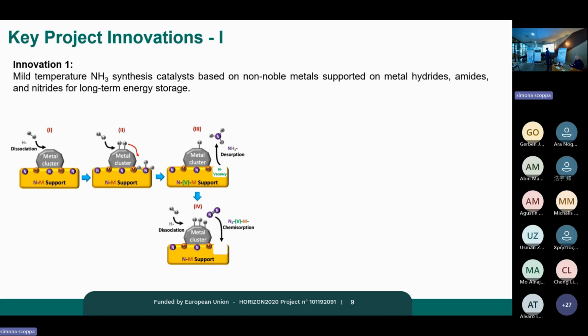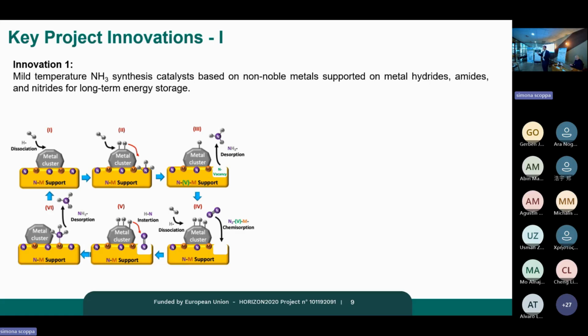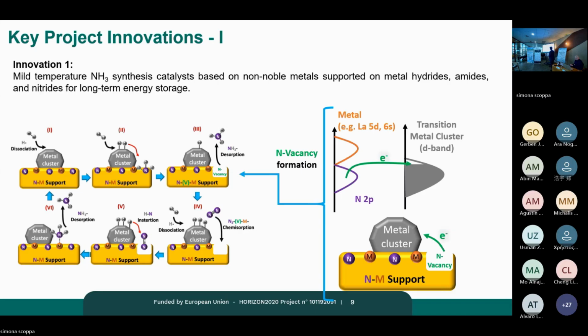the nitrogen, and in that way you can now form a regeneration of the metal nitride and you close the chemical loop. Yeah, and this cycle has been demonstrated by the group of Hosono in Japan, where they have shown a conversion at very, very mild temperatures and pressures. The general idea is that this vacancy, when it is formed, injects electron density in your metal, and that changes the filling of the d states on the metal surface, which makes it very, very reactive.